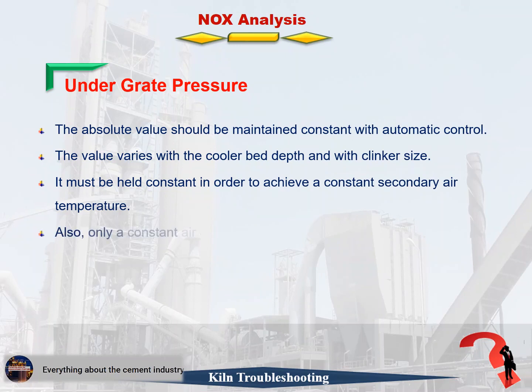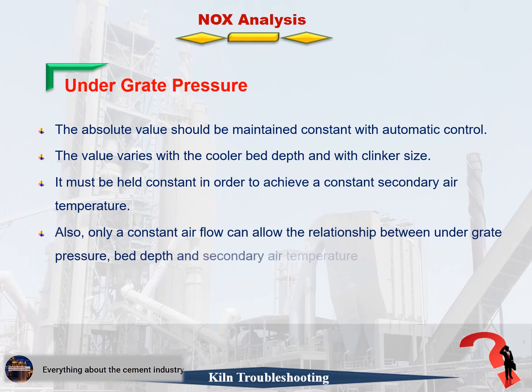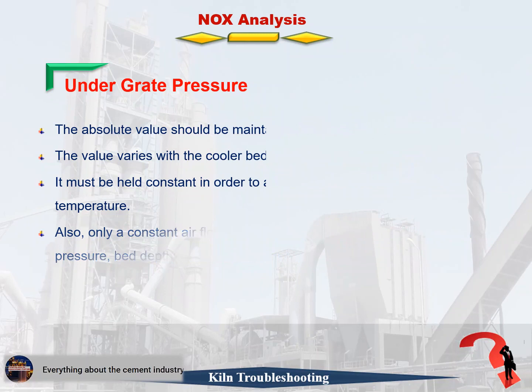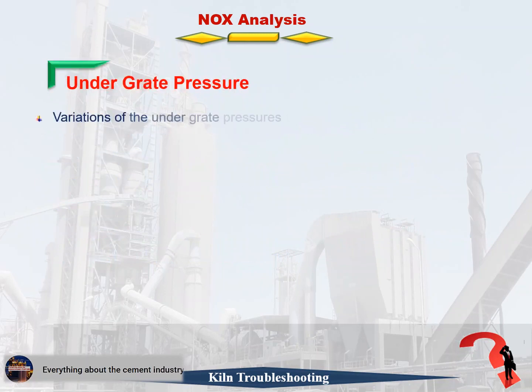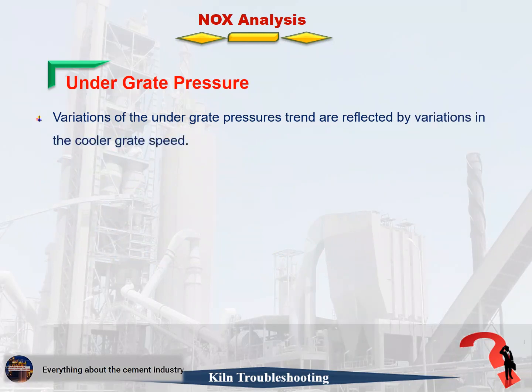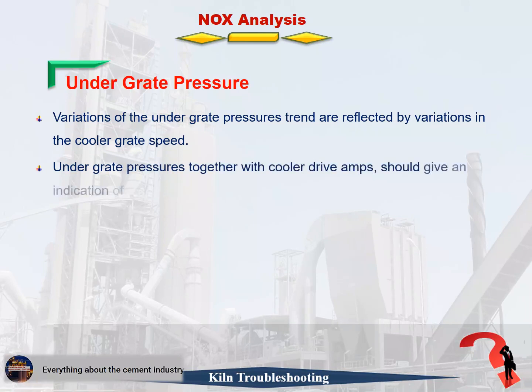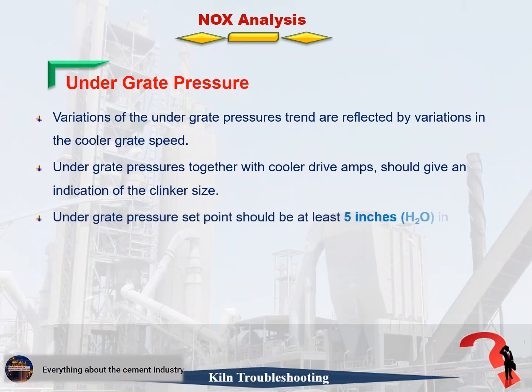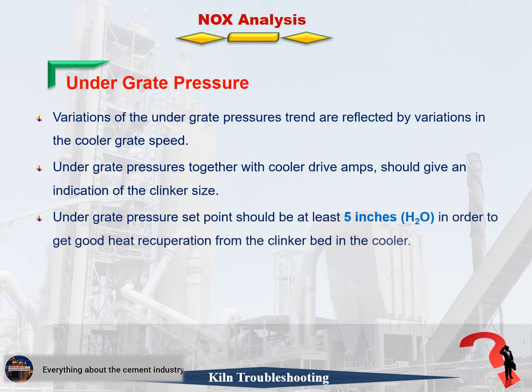Also, only a constant airflow can allow the relationship between undergrate pressure, bed depth, and secondary air temperature to be valid. Variations of the undergrate pressures trend are reflected by variations in the cooler grate speed. Undergrate pressures together with cooler drive amps should give an indication of the clinker size. Undergrate pressure set point should be at least 5 inches H2O, in order to get good heat recuperation from the clinker bed in the cooler.